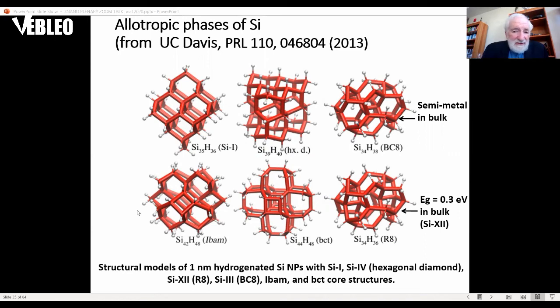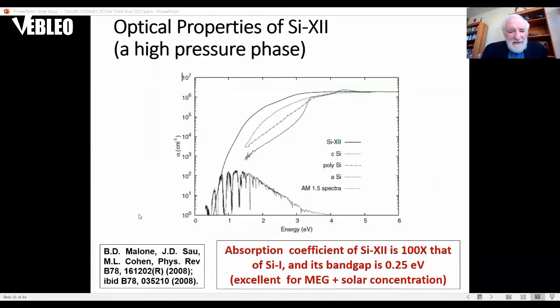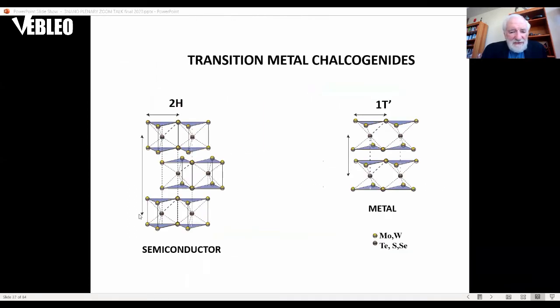The bulk, as I say, is about 1.1, but there are very low band gap phases of silicon, like silicon 12, which has a gap of 0.3. So it puts it into the region where, if you can make it, it's a high temperature and high pressure phase, which is metastable at atmospheric pressure, like a diamond is related to graphite. And so you can produce it, and it has some very interesting properties.